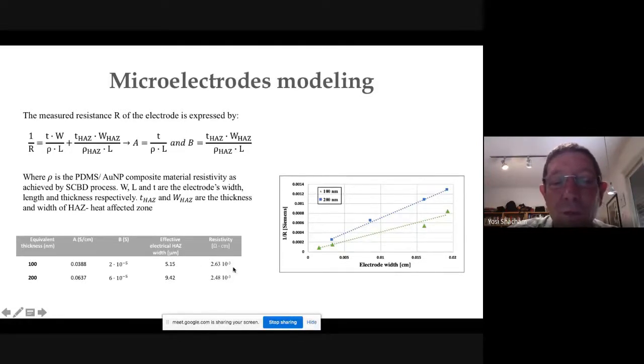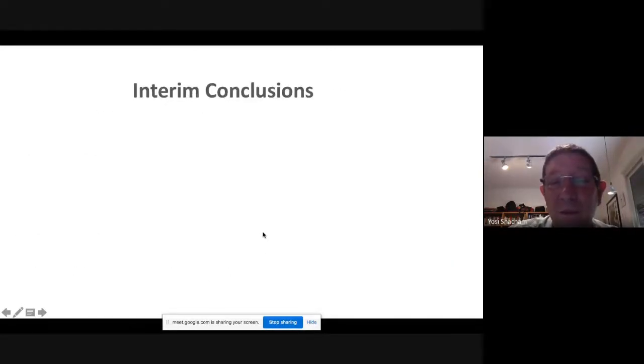Pure gold would be like 4, 5 times 10 to the minus 6. But this is like polysilicon, like indium oxide, like zinc oxide. It's a pretty good material, pretty good conducting, and very, very flexible, really very flexible.